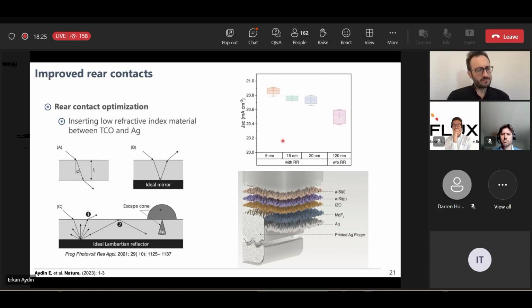After that, okay, we have a good perovskite, but we also did some optimization on the contacts, because we have a lot of losses since a lot of layers are stacked in the tandem cell. Usually more than 15 layers are stacked. In this case, the smart thing is playing with the optics and minimizing the parasitic losses. For this, we used a strategy from the literature. This is not something new, it's a well-known thing, but we adopted it for our tandem cells in a proper way. For these devices, you have to displace the rear metal contact to approach the ideal mirror conditions. You don't want too much plasmonic absorption at the metal-semiconductor interface.